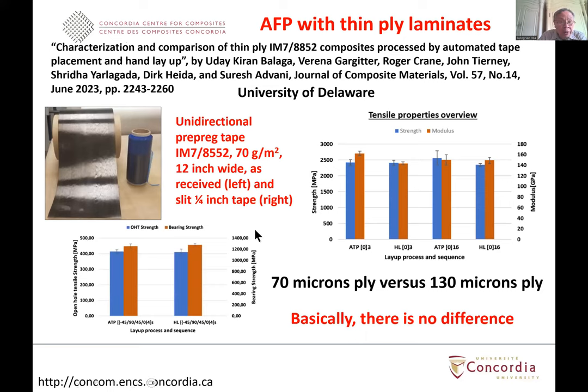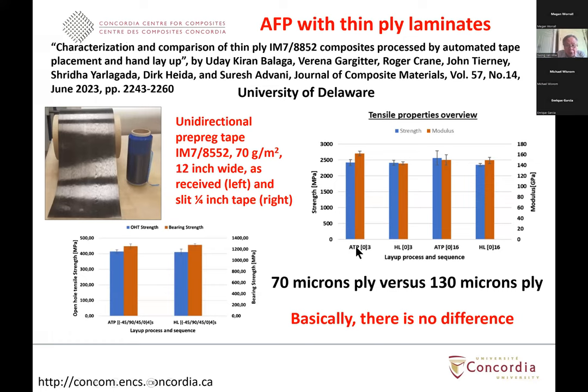So there was some work done at the University of Delaware, and there is a publication this year. They were using the thin ply laminate from IM7/8552. And they were using two different techniques to make the laminate. The first technique is hand layup using a wide tape. And the second technique is AFP. In this case, they were slitting the tape into narrow tape, and laying it down using the automated fiber placement. So the good news is that after they made the laminates, they tested them for different properties, such as the tensile properties and also the open hole tensile, and so on. And basically they found that there is no difference between the two. So in a sense, what it says is that people can process thin ply laminate and have equivalent properties to the one with hand layup, which is, I think, good news for automated fiber placement.